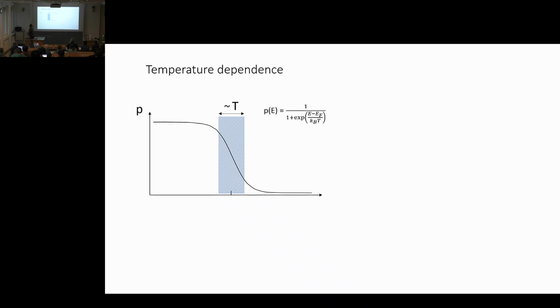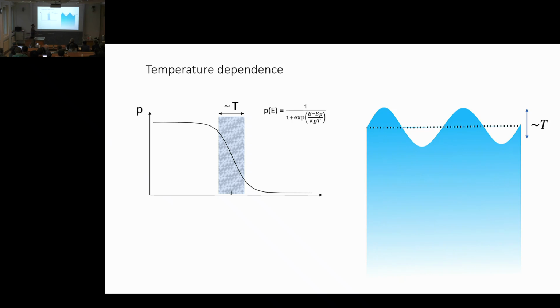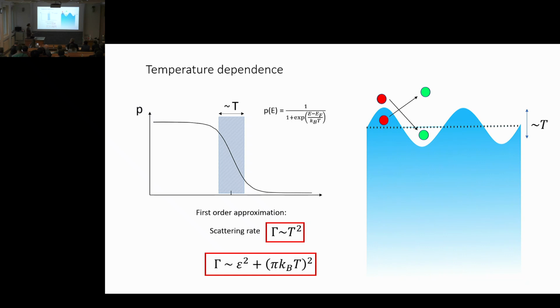We can follow similar arguments with the temperature. The temperature will smoothen out our Fermi edge by a factor of T, for small temperature at least. And then our Fermi edge is starting to be wavy, and we can, in principle, interact with electrons above the Fermi level and also scatter into the Fermi sea where there is space. So again, this leads to a proportionality of T squared, and in total we have the probably by most of these people here well-known dependence of the scattering rate by epsilon squared plus T squared.